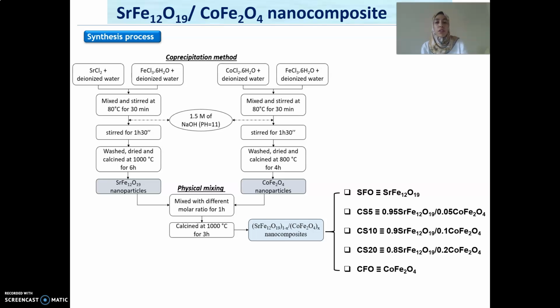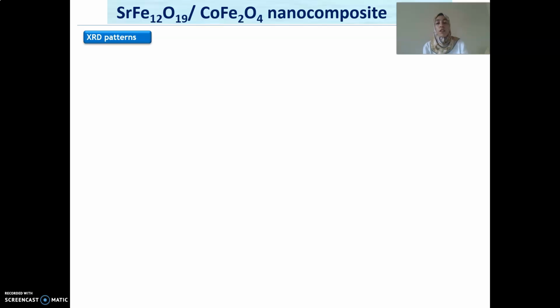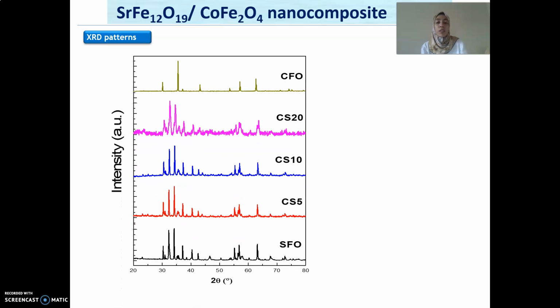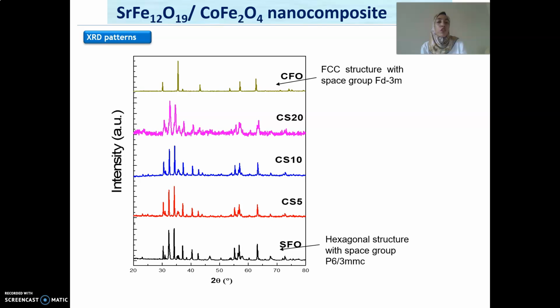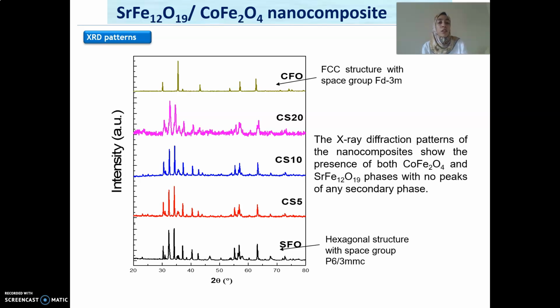From the XRD patterns, we can clearly see that the CFO crystallizes in the cubic spinel structure, and the SFO crystallizes in the hexagonal structure with space group P63/mmc, while the XRD patterns of the nanocomposites show the presence of both cobalt spinel ferrite and strontium hexaferrite phases with no peaks of any secondary phase.